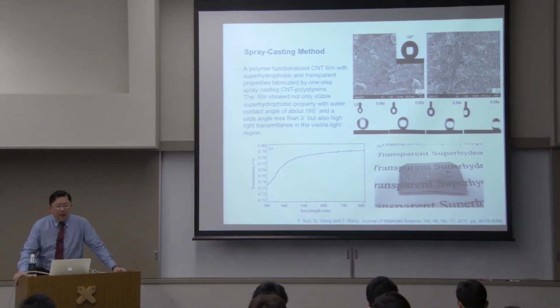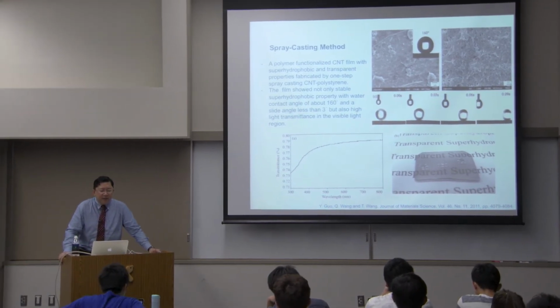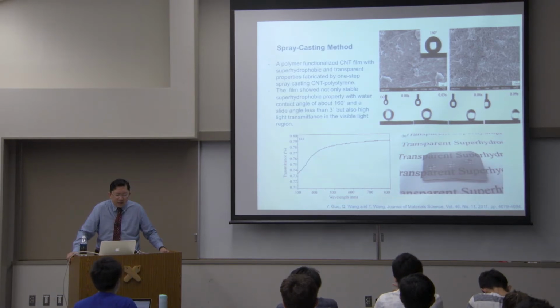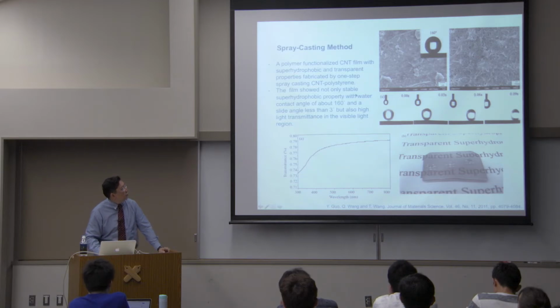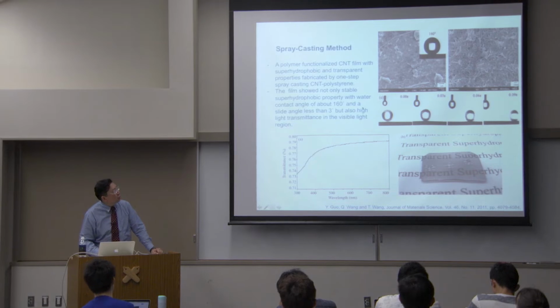Yet another method is based on spray casting. This can be done using a carbon nanotube solution together with polystyrene, and you simply spray the material. The result again is a hierarchy of roughness, and here you have the demonstrated super hydrophobic effect. They also highlighted a sliding angle of less than 3 degrees, meaning this is also a self-cleaning surface.